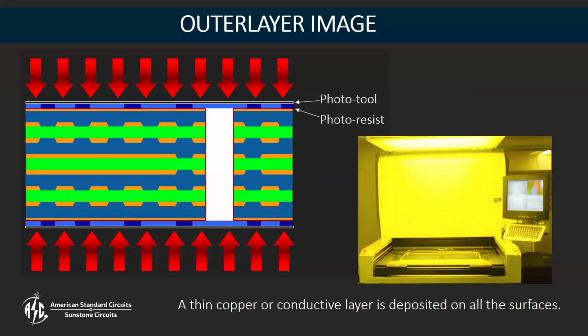Now we're going to go back through the image process one more time, and we're going to put those outer layers on. This time, the polarity of the image is the exact opposite. We are going to use the photoresist rather than as an etch mask, we're going to use it as a plating mask. So we want to expose the copper below it to the areas that we actually want to keep on the panel. And we're going to increase the thickness of those through electroplating.